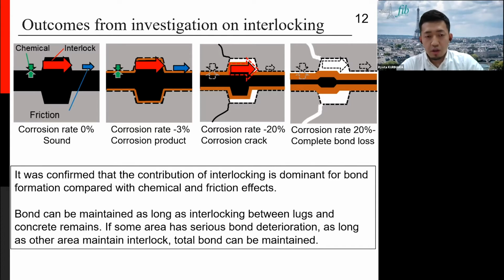I think the friction can work if the rust covers the rebar before casting, because rust is not liquid and solid, so contact between concrete and steel and rust can be kept, I think. But the chemical adhesion is lost in this state. But the most dominant factor of the bond was interlocking, I believe. So if we compare the pure bond resistance, if the rebar is slightly corroded or a sound rebar, the same result can be obtained, I think.